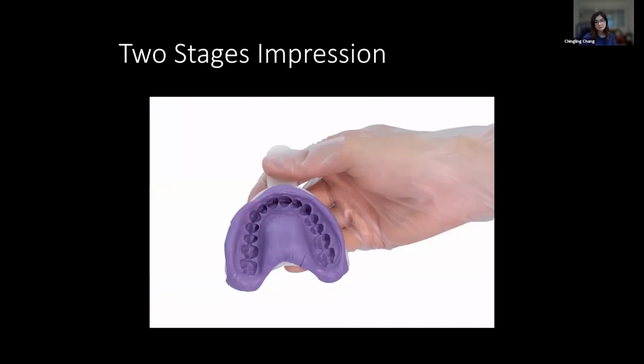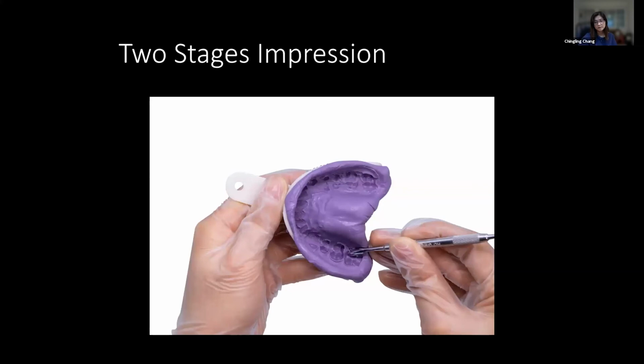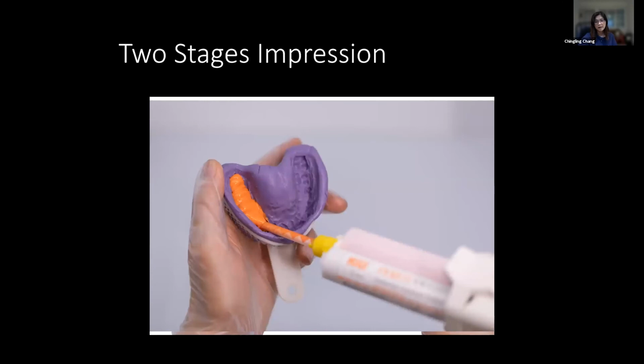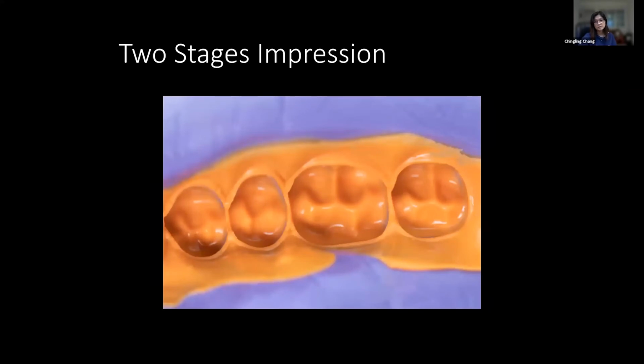And the two-stage impression, you usually use in cases where you have more units. What we do is take the impression with the putty first, and after the material is set, we use a knife to remove the material from the undercuts and all the details. Then we apply the light body again on the putty impression material and on the teeth, and we take the impression. This makes multiple-unit work less stressful, because when you work on multiple units, you have more stress doing the isolation. So you can do the two-stage impression.